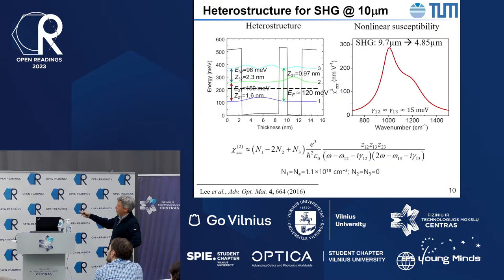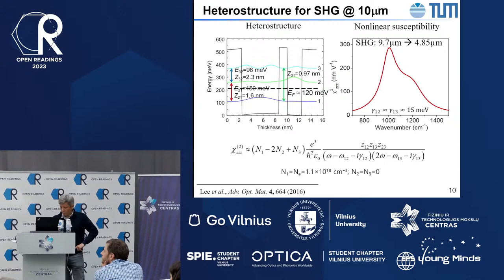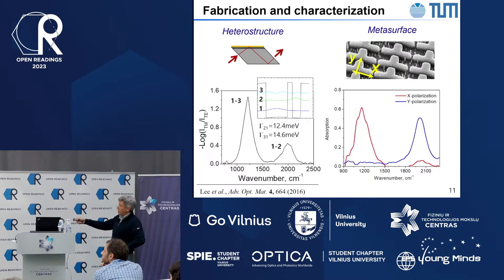We are limited somewhat by this conduction band offset. We cannot really go too visible easily in our heterostructures because our semiconductors have only so much band offset between the conduction bands of the well material and the barrier material. But nevertheless, these are the calculations, and when we implemented it, we could probe optical transitions in this heterostructure by using spectroscopy in this configuration.